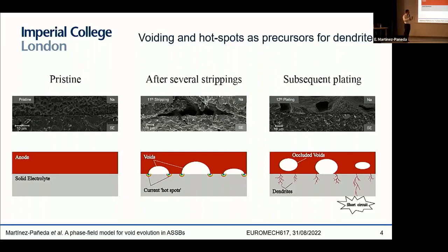And therefore, the voiding process becomes a competition between the rate at which lithium is being dissolved at the interface, which scales with the stripping current density, and the rate at which lithium is being replenished, which is related to the lithium diffusion and also the creep effects that you get from that stack pressure.